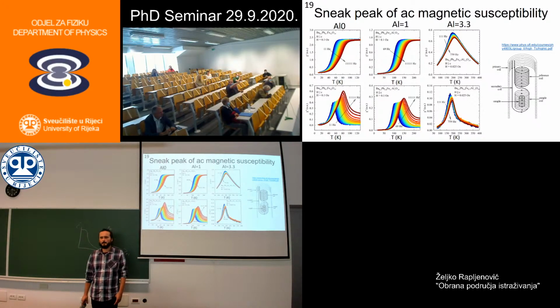But we always measure only odd harmonics. Look, this is the real part of the magnetic susceptibility. This behavior you can also get from a spin glass, exactly the same. I know. But the difference is whether this peak disappears if you measure the 2 omega, so at 222 hertz. I know what you're saying. With the lock-in it's easy to do.